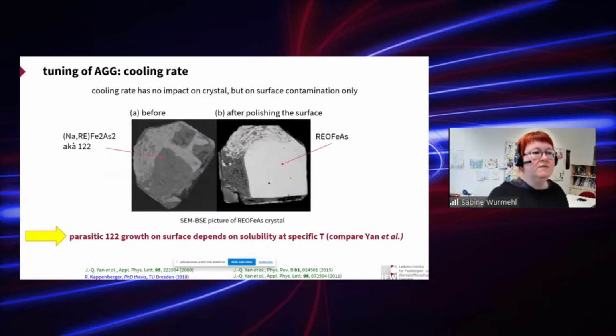Indeed, we can see that slow cooling is not good for the quality of the crystals, because if you cool down very slowly, you have the growth of a parasitic 1-to-2 phase on top of your already grown 1111 crystal. You can remove this material by polishing, and then you really get a clean 1111 single crystal.